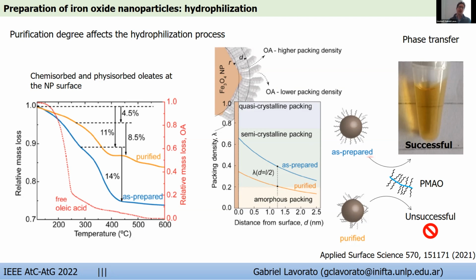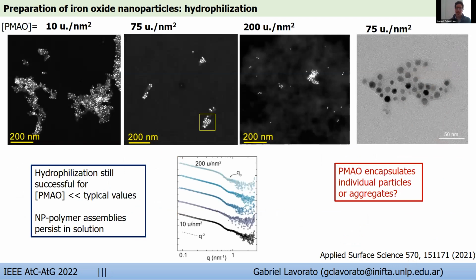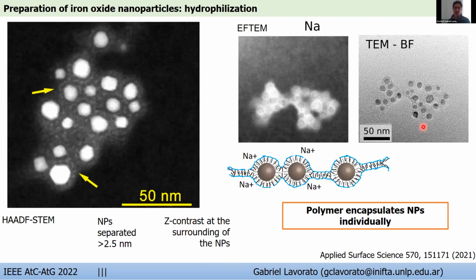So then we studied the nanoparticle polymer assemblies in the TEM, and we found that the hydrophilization still works very well for low polymer densities. But polymer assemblies containing several nanoparticles are still observed both in the TEM and in small angle X-ray scattering experiments. So we wondered if these particles are really aggregated or are individually coated by the polymer. And to answer this, we analyzed some higher magnification and energy filtered images, and the results showed that the particles are indeed well separated, and there is some contrast due to sodium around each of the nanoparticles in these assemblies, which is the counter ion of the solution that contains the nanoparticles. So this suggests that the polymer is indeed encapsulating the nanoparticles individually within each assembly of particle and polymer.